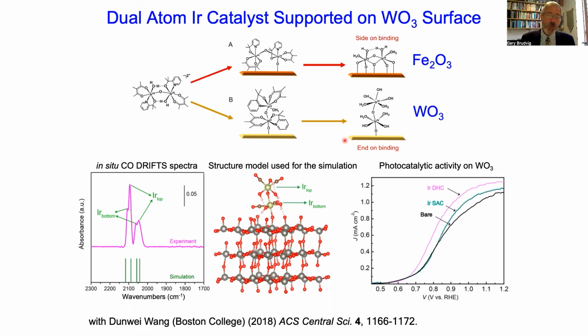But we can confirm that it's still dinuclear by looking at the carbon monoxide frequencies in diffuse reflectance infrared spectroscopy. This was done in collaboration with Matthias Wegle and Dunwei Wang at Boston College. And what we see is a doublet of doublets, which is simulated with this structure here, indicating that we have now an end-on structure, which still is effectively catalyzing water oxidation. We can see the improvement in the photocurrent here as well.